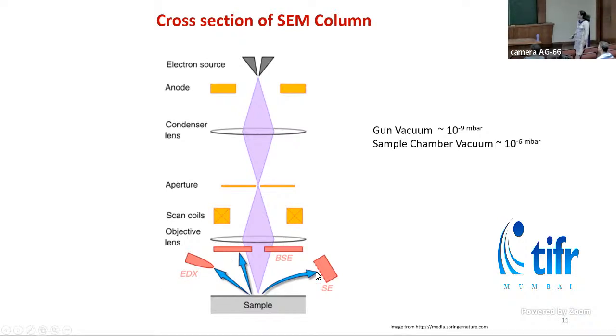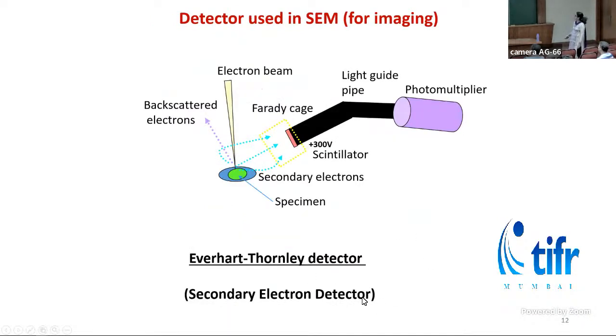Then these are the various detectors used for detecting different signals. This whole assembly is kept in a vacuum, where the gun is of the order of 10 to the power minus 9 millibar, and the sample is at the order of 10 to the power minus 6 millibar. Everhart-Thornley is the detector used for imaging secondary electrons. The secondary electrons emitted from the sample are picked up by the scintillator, which converts the electrons into photons, which are guided through this light pipe, and the photomultiplier tube multiplies those, and hence we can detect the signal.